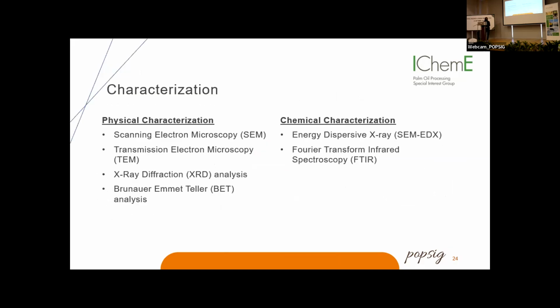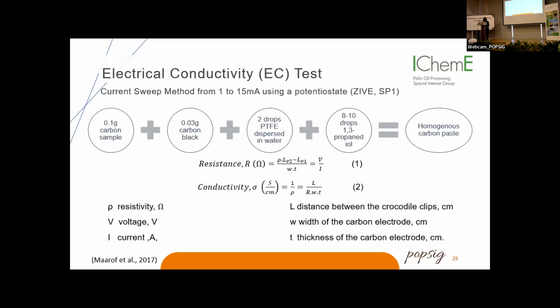The characterization can be categorized into the physical characterization and chemical characterization. Physical characterization involves scanning electron microscopy, transmission electron microscopy, X-ray diffraction analysis, and Brunauer-Emmett-Teller analysis. For the chemical characterization, energy dispersive X-ray and Fourier transform infrared spectroscopy were used. The electrical conductivity test was carried out using the current sweep method from 1 to 15 milliampere using a potentiostat.